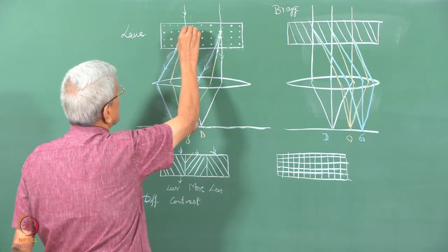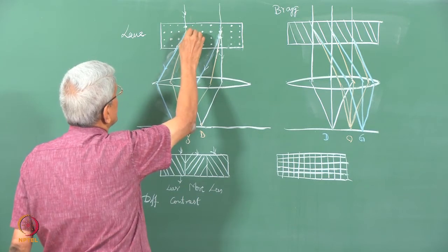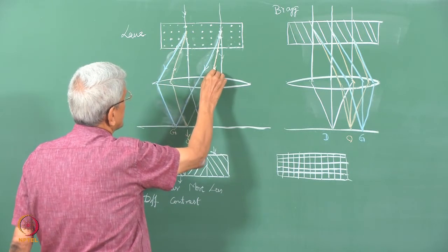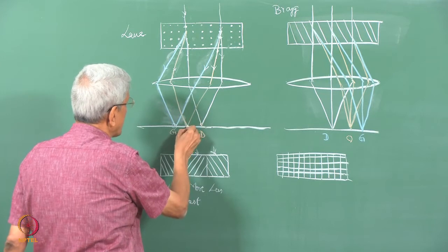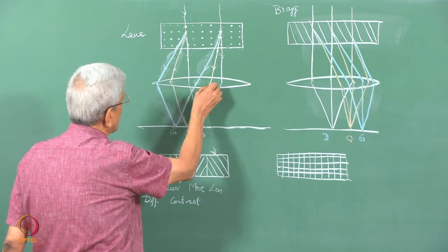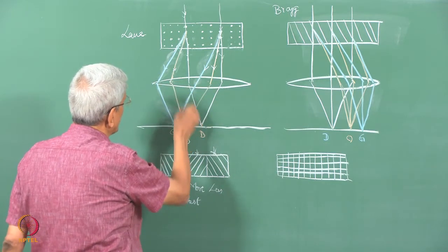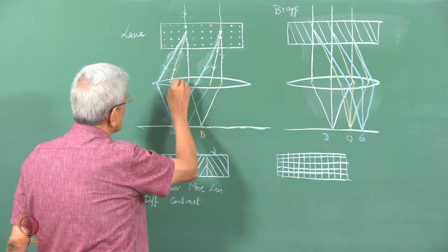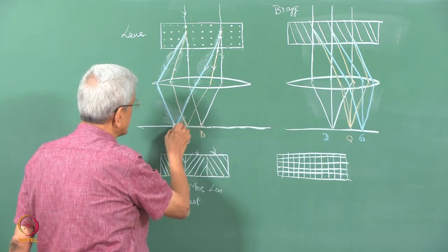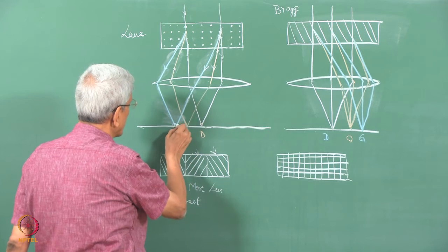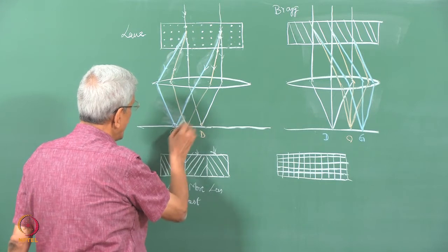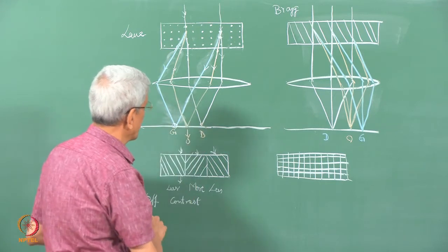But we know that from every point the incident wave is scattered in various directions. So, if we look at this particular direction, and find the net amplitude of the wave arriving at this point, all of them have different signs, so the net amplitude turns out to be 0. That means that only at some specific scattering angles the amplitudes add together, giving rise to constructive interference. In other cases the amplitudes can be less than this, and in some cases the amplitude can become 0.